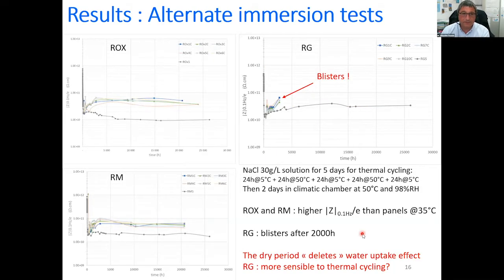Now, these are the results for the alternate immersion test. So the free defect panels were submitted to this test. And as you can see here, the ROX and RM systems show higher values for the reduced impedance modulus than the values that were observed in the immersion at 35 degrees C. But for the RG system, we had a problem. In fact, we observed some blisters after 2,000 hours of this test. So again, for ROX and RM, we can observe that the dry period in the test seemed to delay the water uptake effect. And for the RG system, we've got maybe a system that is more sensible to thermal cycling.